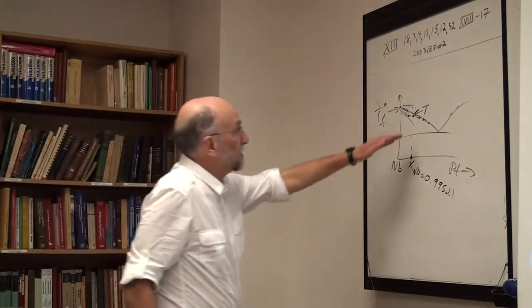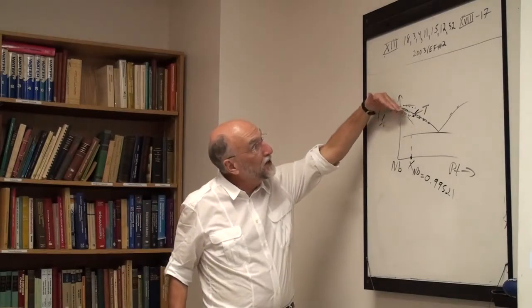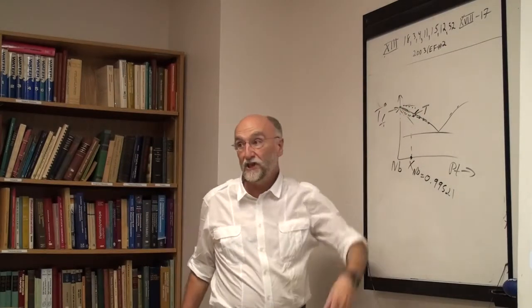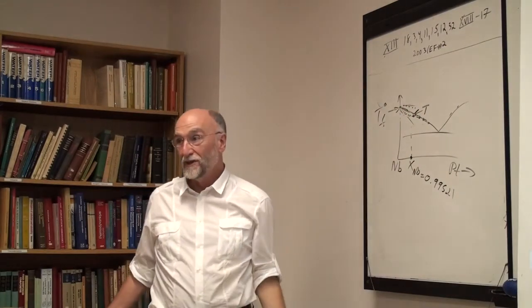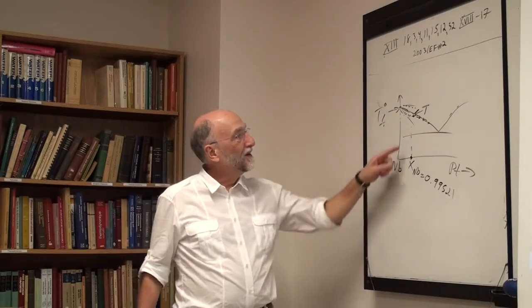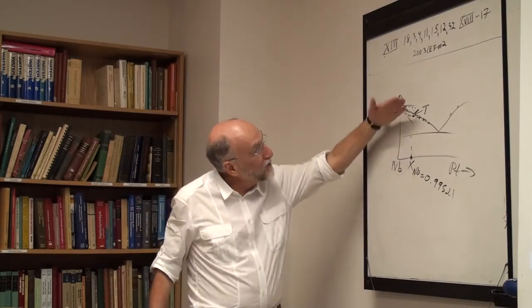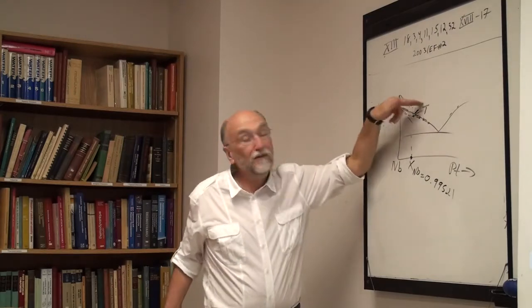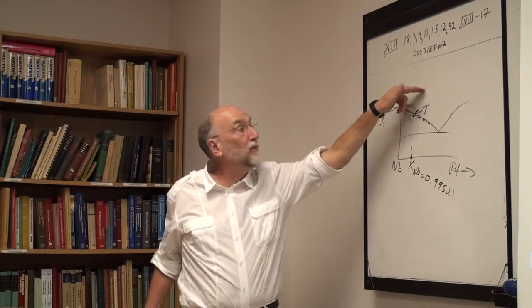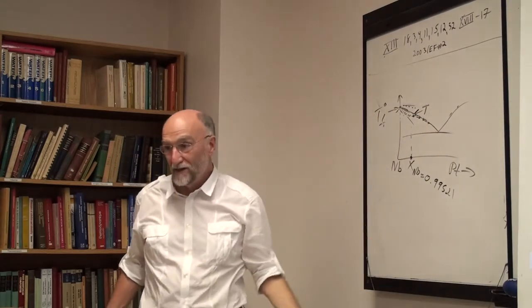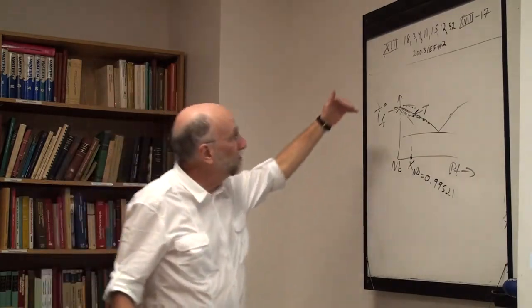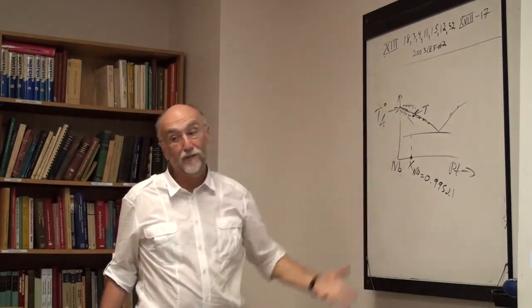But you can't fix this up in the limiting region. In the limiting region, you can't fix up your liquidus just by adding more G-excess terms, unless they're huge, and that's just not right. You can add very big G-excess terms, which will kind of bend this in, but it's going to throw everything else off over here, because that's not the problem. The problem is the ideal term, the experimental data, the heat diffusion, something is wrong.